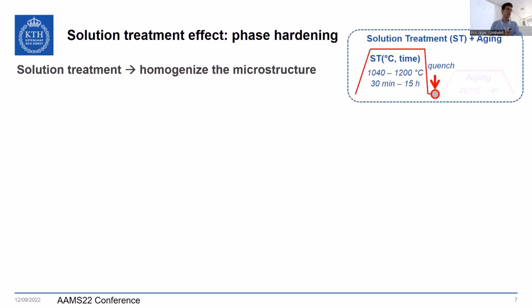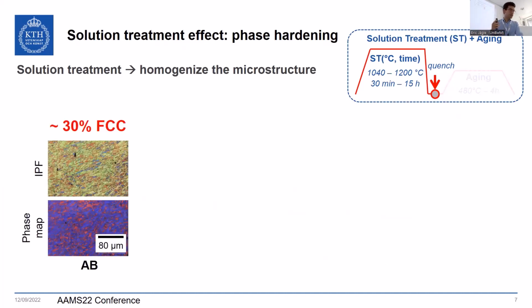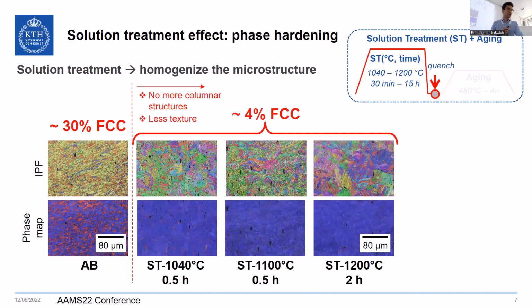So one strategy is to apply this solution treatment. Solution treatment will have the effect of homogenizing the microstructure. We pass to austenitization and then we quench. So here is the as-built microstructure for record, and then we have the microstructure after the solution treatment and quench.